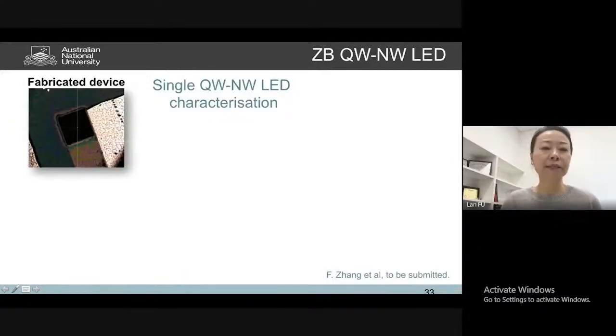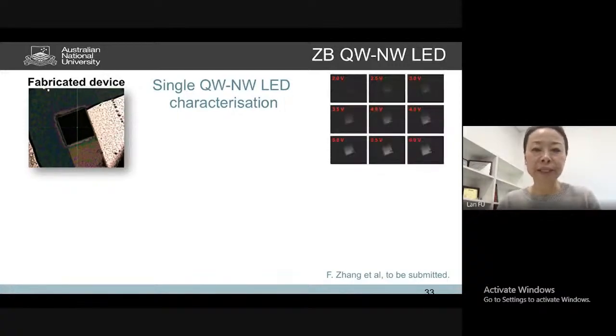So now we look at the LED. We fabricate them into the LED device by contacting the top with the ITO layer. Basically, it's a transparent oxide conductive layer to contact our LED. And then we inject current at different bias voltage. You can see at different bias voltage, the light becomes brighter and brighter from this nanowire array.